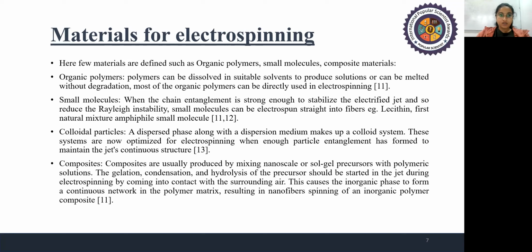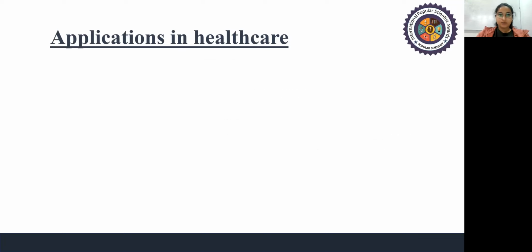The composites are then electrospun, which are usually produced by mixing nanoscale or sol-gel precursors with a polymeric solution. The gelation, condensation, and hydrolysis of the precursor should start in the jet during electrospinning by coming into contact with the surrounding air. This causes the inorganic phase to form a continuous network in the polymeric matrix, which results in nanofiber spinning of an inorganic polymer composite.